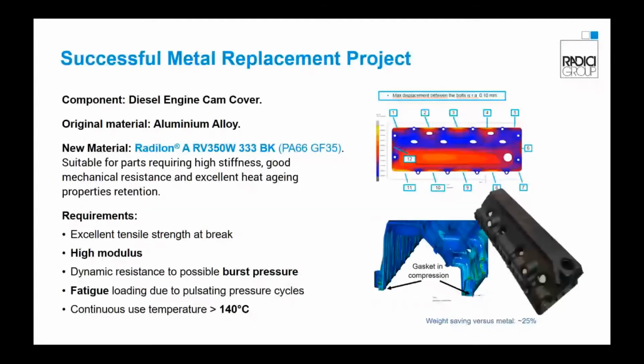This is another successful metal replacement project on a diesel engine cam cover. The original material for this application was aluminum alloy, and RadiciGroup was able to support the customer, providing a dedicated CAE service and a material solution. The proposal from our side was a polyamide 66 with 35% of glass fiber, with high stiffness and good mechanical resistance, and an excellent heat aging properties retention. Requirements also in this case were high mechanical properties, fatigue, and creep resistance, as well as continuous use in temperature.